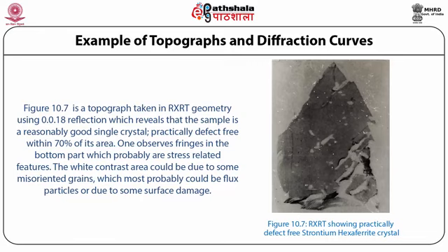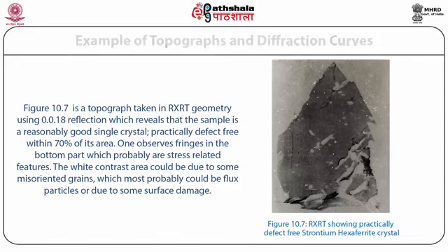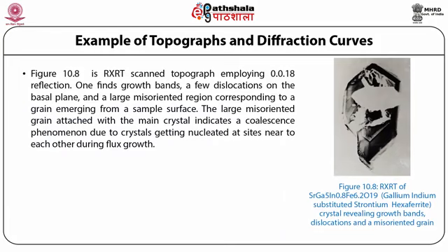One observes fringes in the bottom part, which probably are stress-related features. The white contrast area could be due to some misoriented grains, which most probably could be flux particles or due to some surface damage. Figure 10.8 is RXRT scan topograph employing